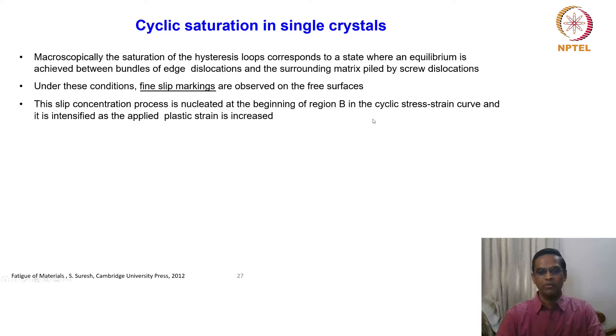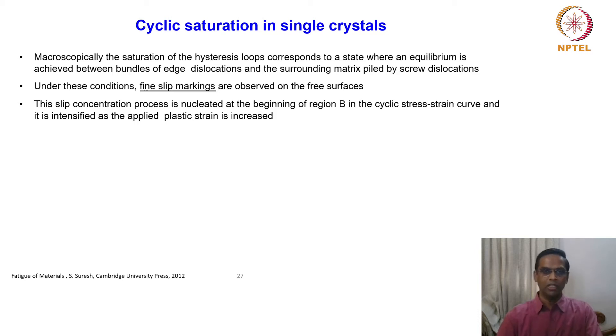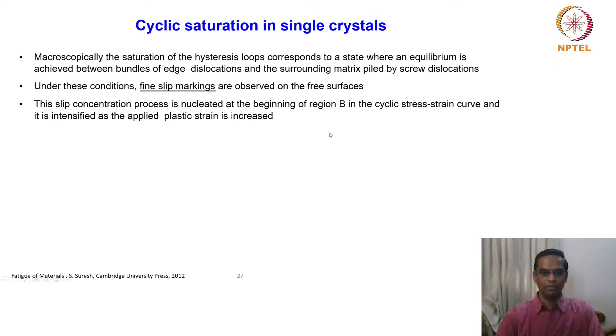We are now talking about the three stages of the cyclic stress-strain curve: A, B, and C. We discussed in the last lecture how to generate this cyclic stress-strain curve — the peak tensile stress of all hysteresis loops are connected from the first cycle to the saturation cycle, and then analyzed as a shear stress versus shear strain curve. We are now looking at the beginning of region B and the microstructural aspects accompanying that deformation.